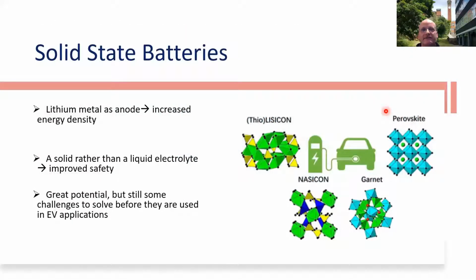And the other interest, and there's a huge amount of interest in the news about this, and these are seen as the next step, is the solid state batteries. So I mentioned at the start, your conventional battery has a liquid electrolyte. It's a lithium salt in a hydrocarbon solvent. And so one of the issues with those is you can't use lithium metal as your anode, otherwise it would give safety implications, and that's why you use graphite or one of these other electrodes.